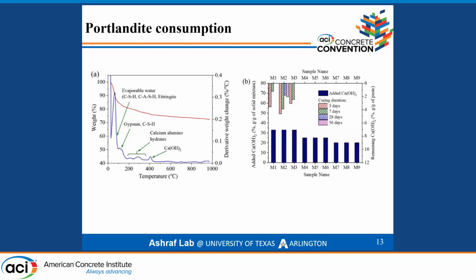As you can see from this plot, our M1 and M3 batches consumed all the Portlandite at 28 days. But in our M2 batches, 2% Portlandite still remained after 56 days of curing. But in all other batches, from M4 to M9, all of the Portlandite was totally consumed within the first 3 days of curing. The calcium ion from the Portlandite reacts with the alumina from the calcined clay and forms some reaction product. That is how the Portlandite is consumed. So we can say that the more alumina we have in our system, the faster the Portlandite will be consumed.